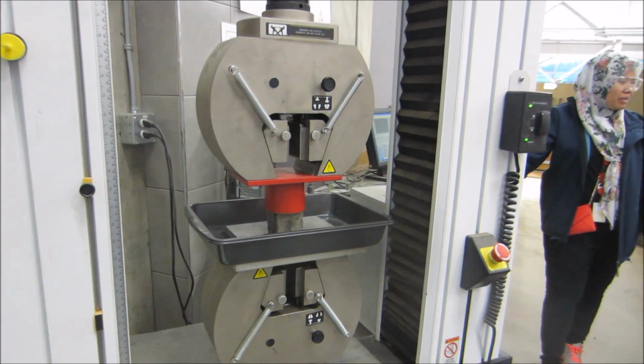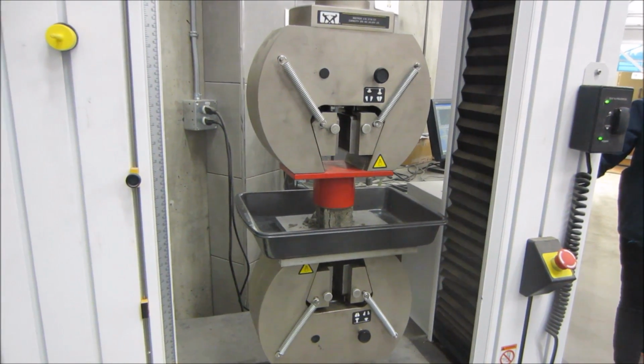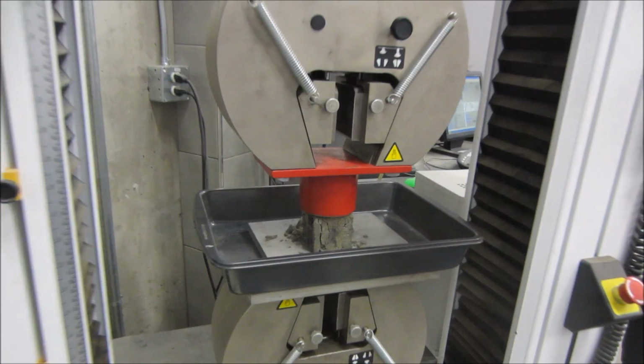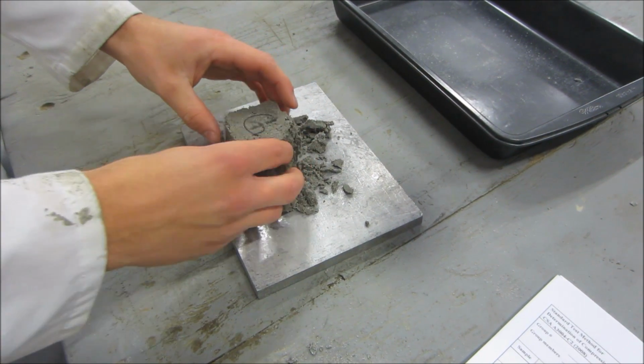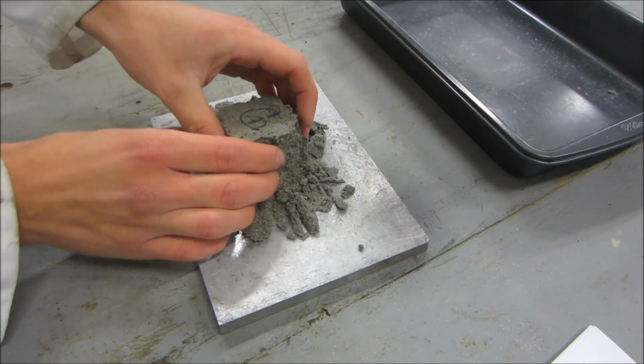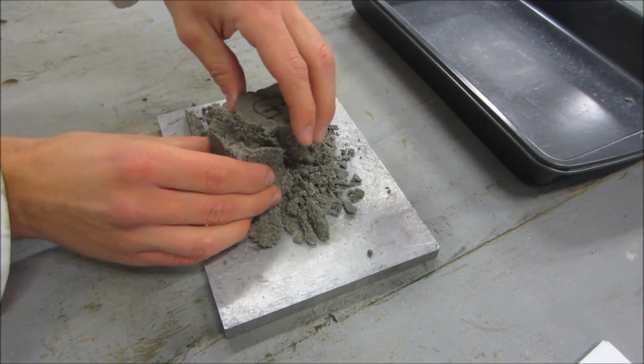Place the specimen in the testing machine and apply the loading until the specimen fails. Make observations of how the specimen failed and record the maximum load as shown on the testing machine.